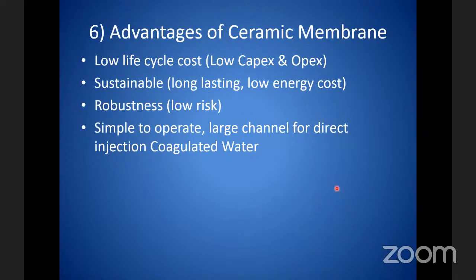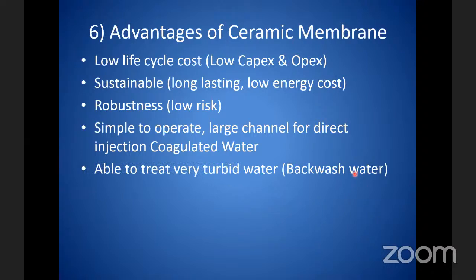It is simple to operate, with a large channel for direct injection of coagulant. As you saw just now, the channel is 2.5 mm, so it won't be so easy to clog. You can push it, and with the backwash of 5 bar, it will not clog the channel or the membrane, not like a normal hollow fiber. If you use coagulation assisted filtration in hollow fiber and the channel is not big enough, you may have that problem. You clog the channel, not the pore of the membrane, but the channel that goes into the hollow fiber. If you have a bigger channel, such as multi-bore, you will have some advantage like that. But with multi-bore, you may not be able to use polymer or organic coagulant, because it will blind the polymeric membrane. So it is able to treat very turbid water, such as backwash water.